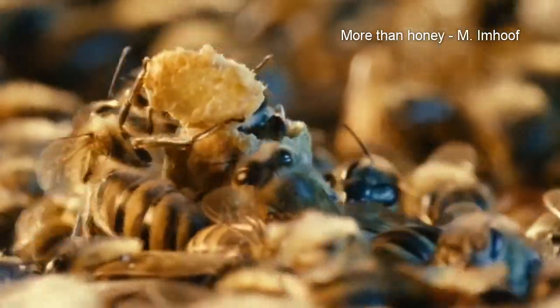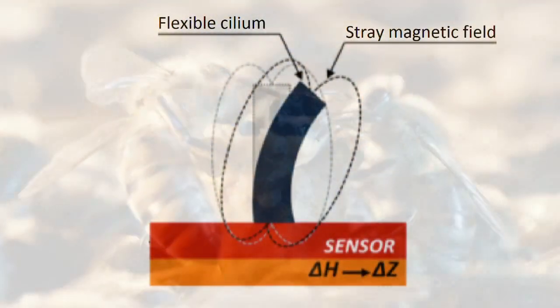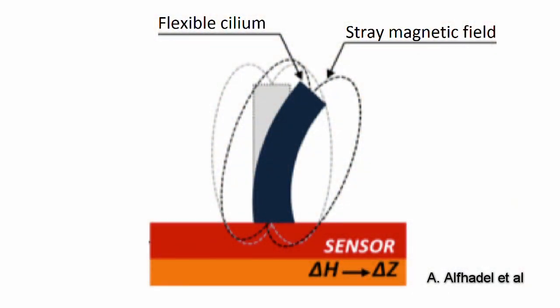To imitate this structure, we will be needing an array of pillars patterned and anchored to a sensor that can detect the pillar's movement and displacement. The implementation of such a setup can be made by patterning a flexible material with permanent magnetization over a thin film sensor detecting the magnetic field incident over it.